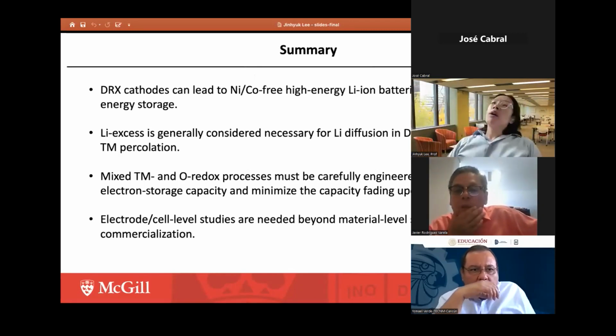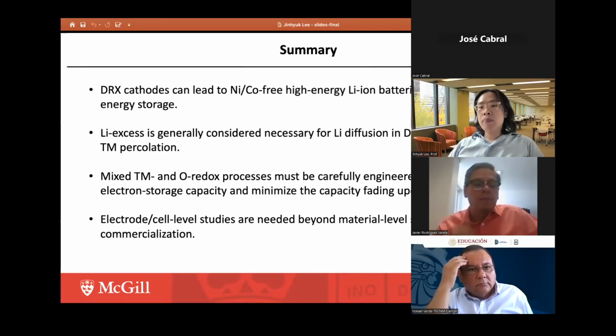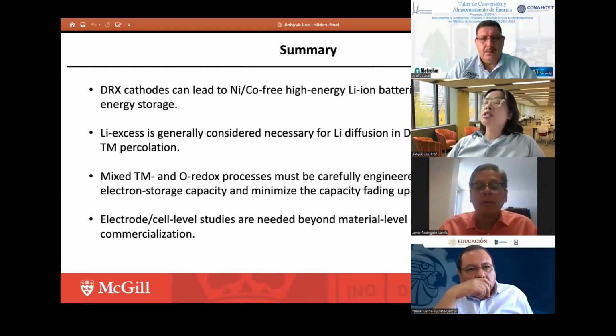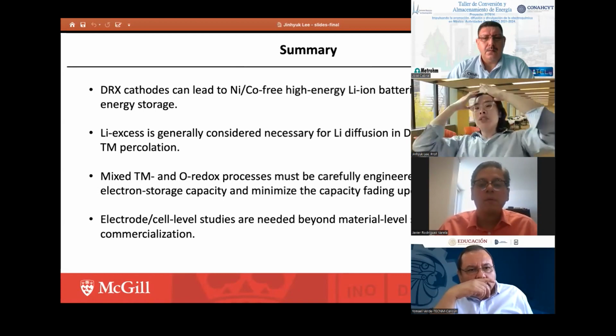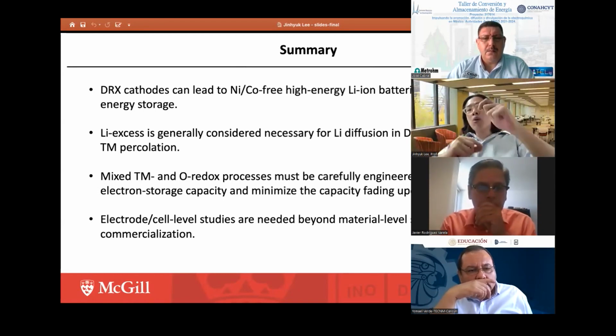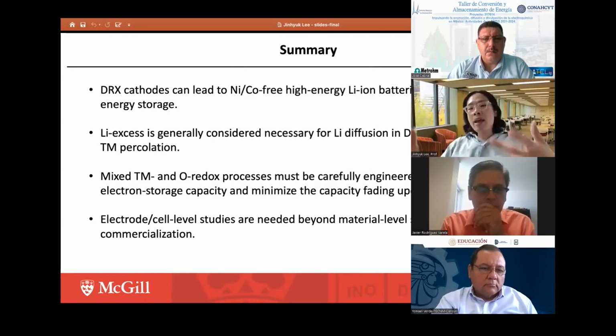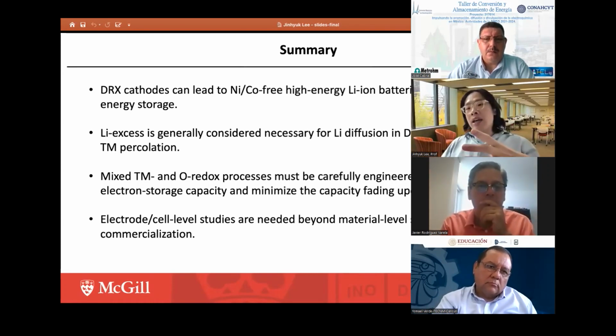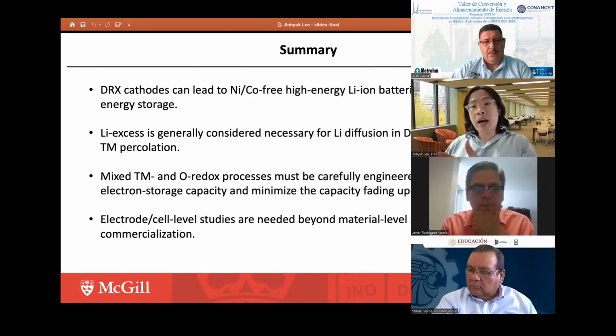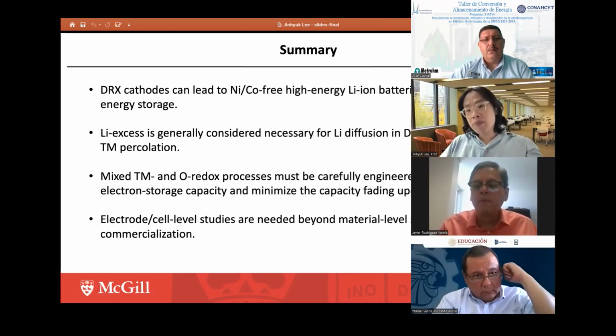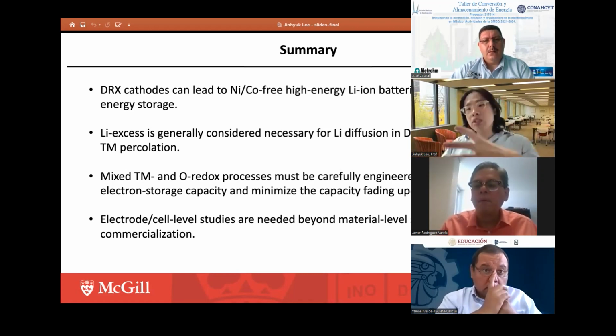So we hope that this DRX structure is also possible for the sodium-ion battery, but generally it is more difficult to make a disordered rocksalt sodium-ion cathode, because when you think about the disordered or the layered structure, this kind of cation ordering happens to lower the crystal energy. If you want to promote disorder, it is more favorable if the alkali metals such as lithium or sodium have an ionic radius more similar to the transition metal. Now, in the disordered rocksalt, the lithium ion is much bigger compared to the transition metals, which are actually smaller ions. So the ionic radius difference between lithium and the transition metal is smaller.